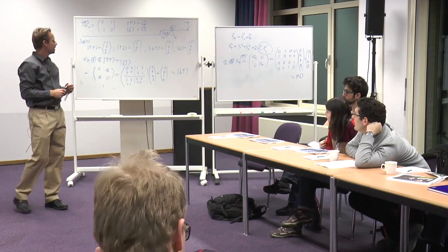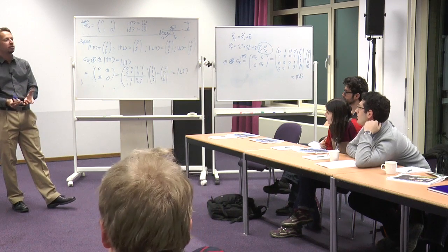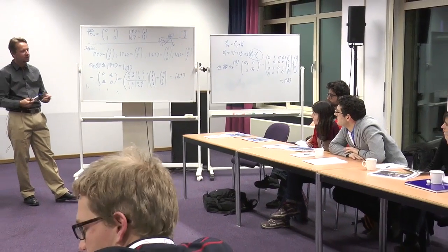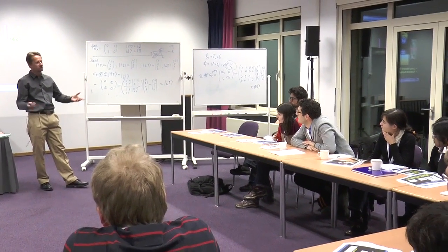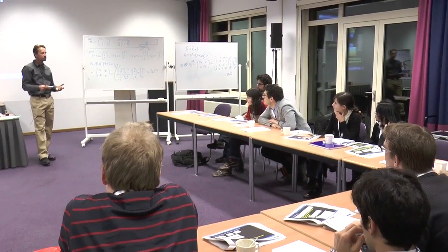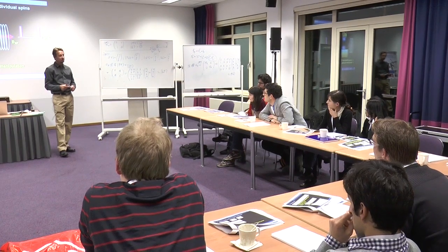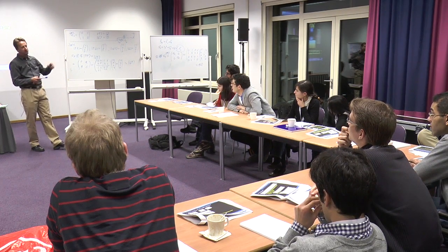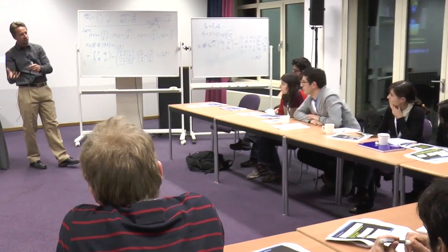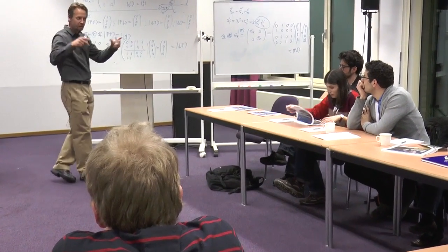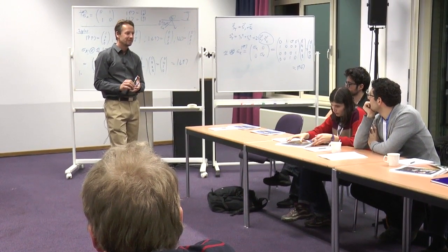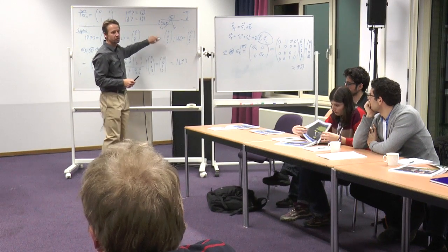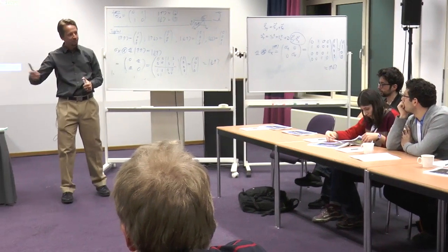I mean, there are many examples where point defects in a material can have very long relaxation times. The fashionable one today is the NV center in diamond, which has relaxation times up to milliseconds or longer, right? T2 and T1. Phosphorus in silicon is another one. Relaxation times can be very long. So I don't think there is a very general reason to expect them to be long or not. You have to really work hard on your local symmetry and so on. The beauty that we have is quite a bit of flexibility, right? We can build different atoms, different surfaces, different structures. So the phase space of possible experiments is huge. But we have a problem with these conduction electrons, which we have to solve for sure. So one step at a time, I would say.